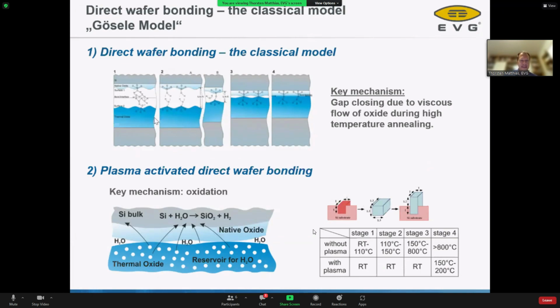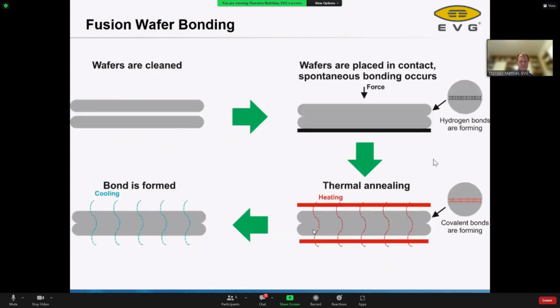Here on this slide, what I wanted to show is that even after chemical mechanical polishing, even if you have probably the flattest surfaces in the world you can think about, if you bring the two wafers in contact, you will still have gaps in the interface. And in order to close this gap, we are applying a trick. We have a so-called plasma activation, which means that we are disturbing the crystallographic structure of our interfaces. We are enhancing the entropy in my system. And then with a very moderate annealing temperature, I can start a recrystallization or reorientation of the crystal lattices of my oxide layers, and I basically get a gap filling. And also with fusion bonding, we are able to achieve bond interfaces without any gaps, without any voids.